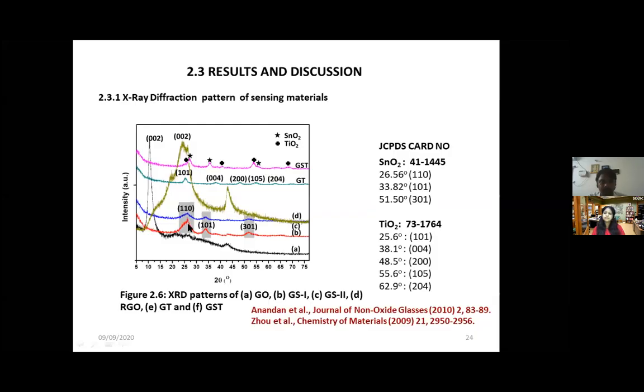The same material, with two different procedures, we can observe that the peak here for GS1 is intense and narrow, but here it is broadened for GS2. And 110 is the dominant peak for SnO2 compared to 101 and 301. And for TiO2, 101 is the dominant peak. And for the ternary composite, we can see the characteristic peaks of both tin dioxide and titanium dioxide.